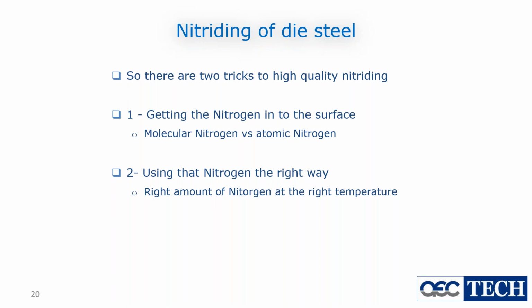They are too big as a pair to go into the surface of the steel. We need in our nitriding process to make atomic nitrogen. That's atoms of nitrogen available to diffuse into the steel. That diffuses in pretty good. The N2, the nitrogen molecule, which is in the air around us, it doesn't diffuse into steel at all well. Good job, really, because we make containers to hold nitrogen of steel. So I don't know how we hold nitrogen if it could diffuse through steel.